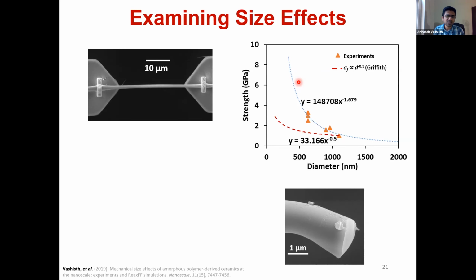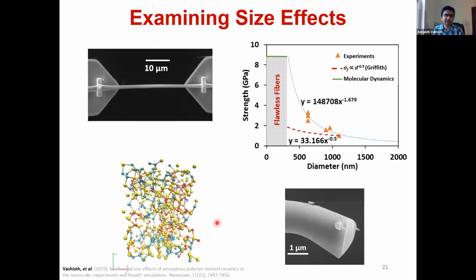Our initial thought process was that the strength of these fibers would go according to Griffith theory, which says that the strength is inversely proportional to the square root of the flaw size. We assumed that the biggest flaw that you can have is the size of the diameter of the fiber. But that didn't quite happen. We saw a much more rapid increase in the strength. So that got us thinking about what exactly could be happening. We kind of had a clue what was happening.